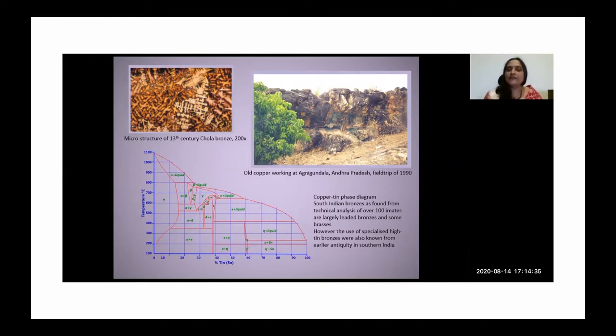And when this composition is reached and at this high temperature, the bronze seems to have been forgeable to a very great extent. And that was how they were able to work out that vessel. And then when they rapidly cooled it in water, the beta phase is quenched. And the quenching of the beta phase is very important, because that prevents the embrittlement of the bronze and it gives it various other properties, which I will point to as we go along.